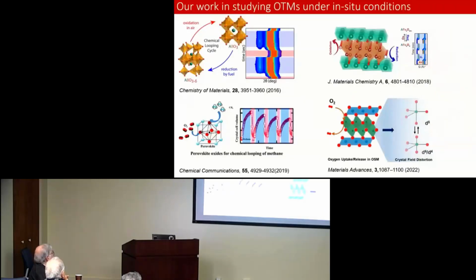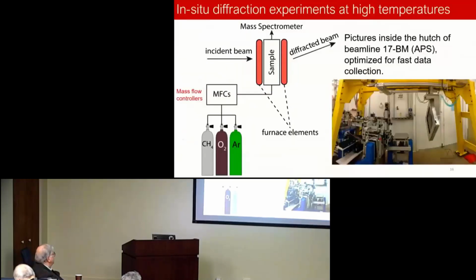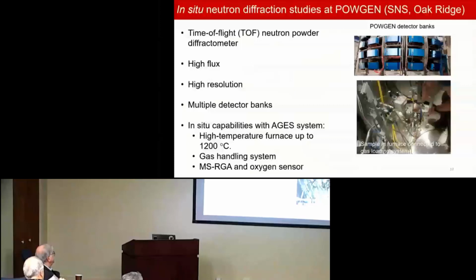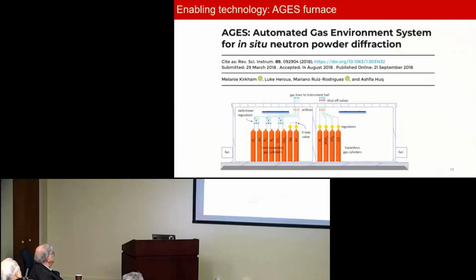These are some of our papers where we do looping between, say, a perovskite and something related to a perovskite, like a brownmillerite type phase. And we cycle them in methane and also in oxygen. I want to say a little bit more about the experiments. My students have been going out to 17-BM, hopefully again soon, to do these experiments, and also to POWGEN, since we're still looking at spallation neutron source, now at Oak Ridge, of course. And shout out to Ashfia for building the AGES system out there to be able to do this kind of experiment where you can put your material in different kinds of environments, such as methane, hydrogen, and so on, and do these cycling experiments.